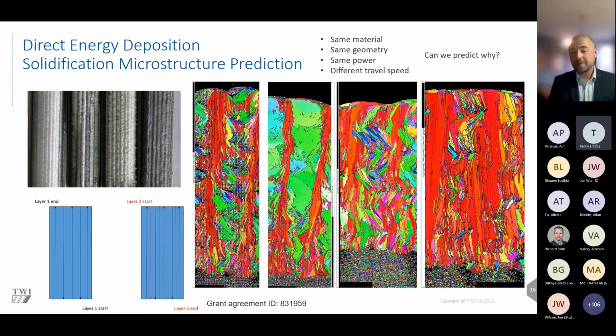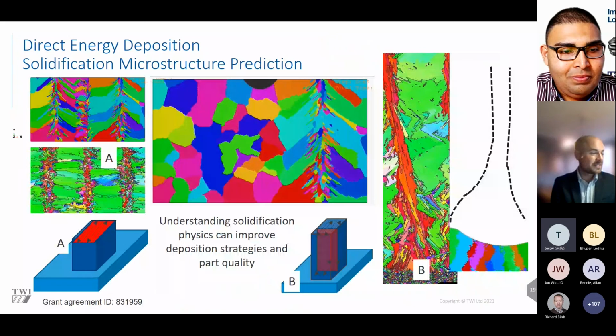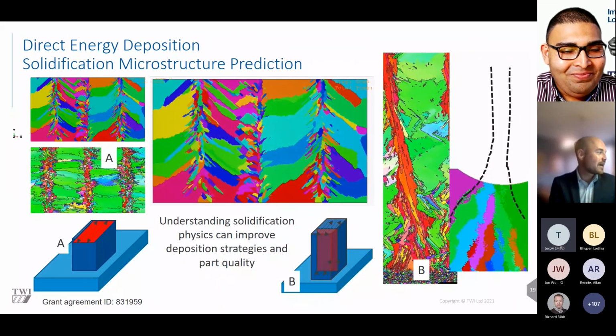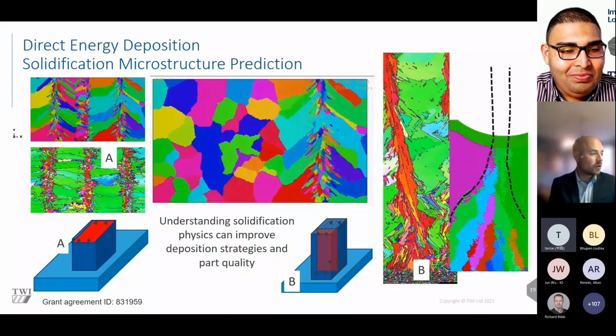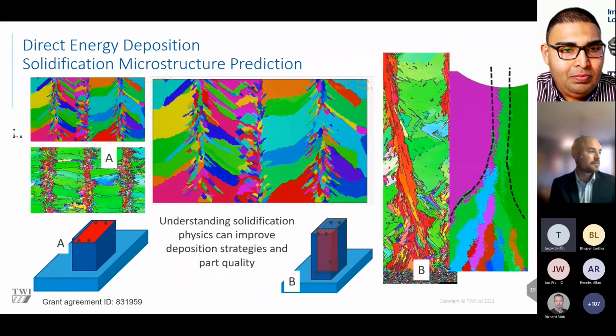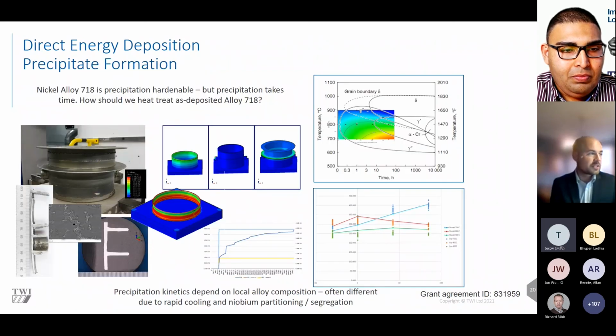Quite a few of these are totally undesirable from a mechanical point of view, but if we can understand why we get certain ones, then we can start to change the parameters virtually without having to constantly build and change parameters in the wall. And so just to summarize these last ones, we can see how these models can look at melt pools and their overlaps and how they link together and how all the changes of the speed relate to that. And we can link them to precipitation kinetics and link that to the strengthening mechanisms. And again, like we were doing in powder bed fusion, we can have tools to understand how our materials behave and how we can improve them.